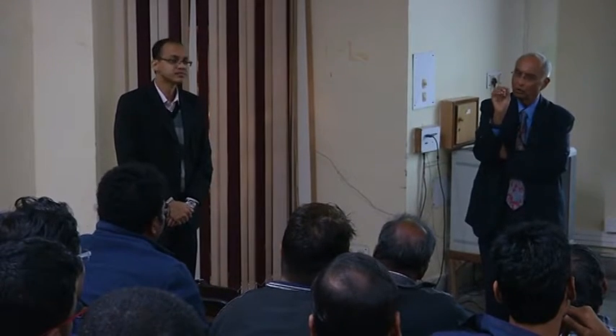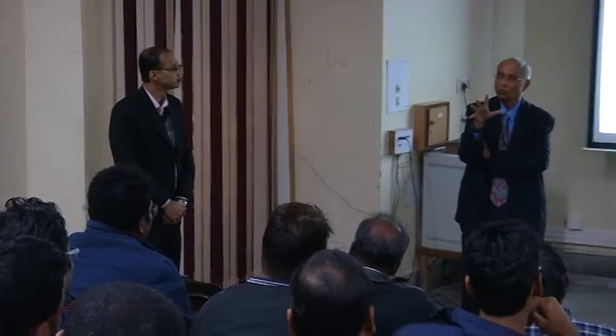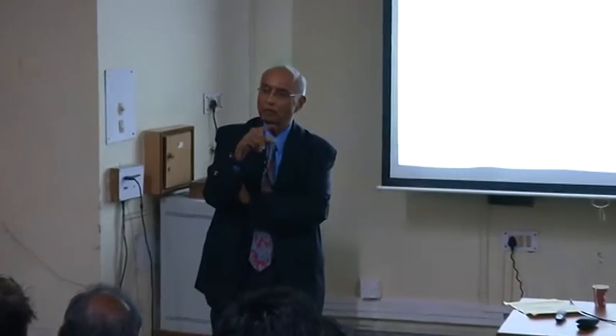Fly ash, if it is solid fly ash, it's an aluminosilicate, so the density will be 2.9, close to that, depending upon the alumina silica ratio. But if it is hollow, that 2% of the fly ash that is hollow, the density is 0.4. It's a hollow microsphere. So how are you able to get this dispersion? That is what I do.